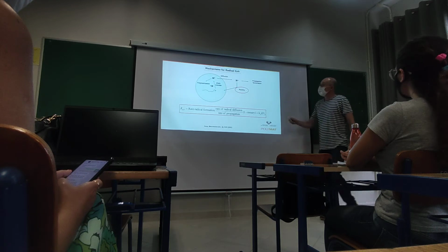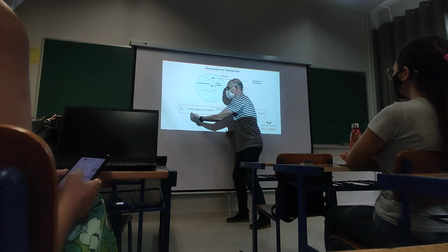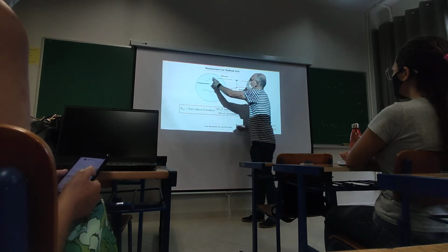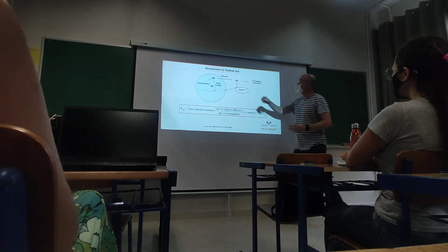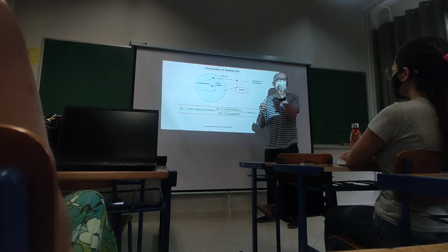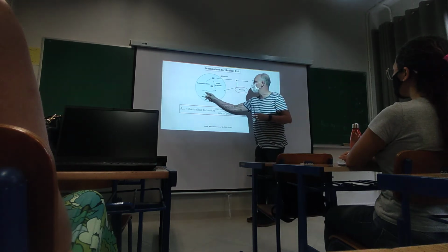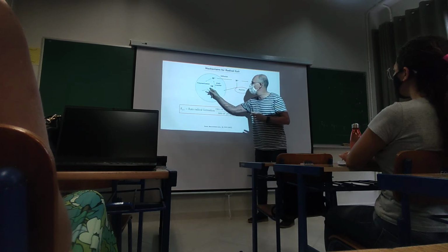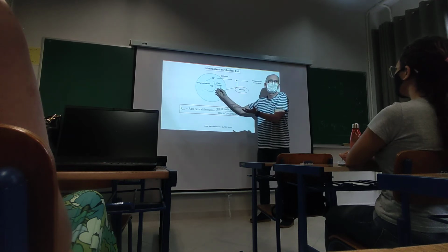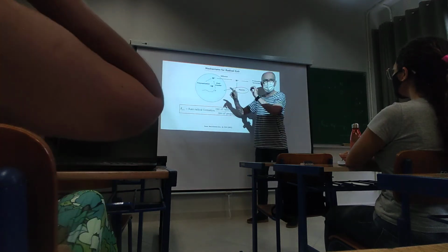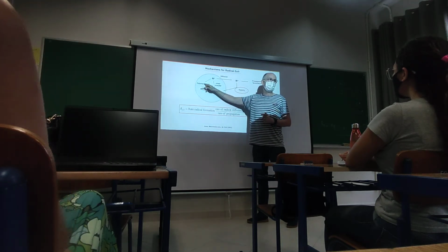Okay? So, therefore, to have exit, we need first to calculate the rate of formation of these monomeric or short radicals. These radicals can exit because they are small, the diffusion is fast or can be fast. Much faster than the diffusion of the long radical. That's why we don't consider that this one exits, because its diffusion is very slow and it terminates before it can exit. But this one moves fast because it's small and can exit, but it can also propagate here.